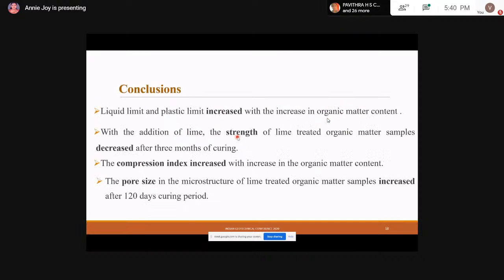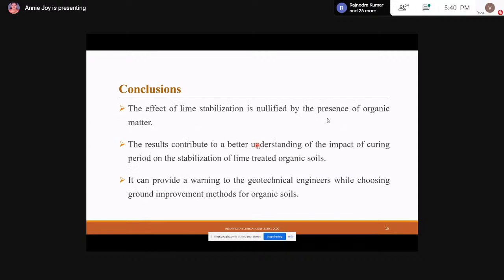So coming to the conclusion, liquid limit and plastic limit increased with the addition of organic matter, the strength decreased, compression index increased, and pore size increased. So from this, we could conclude that the effect of lime stabilization is nullified by the presence of organic matter. So these results really contribute to a better understanding of impact of curing period on stabilization of lime-treated organic soil, and will surely provide a warning to the geotechnical engineers while choosing a ground improvement method for organic soils.